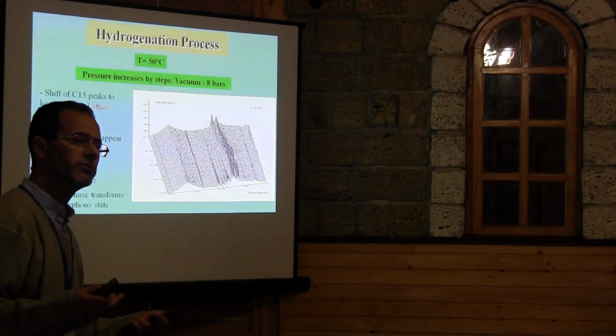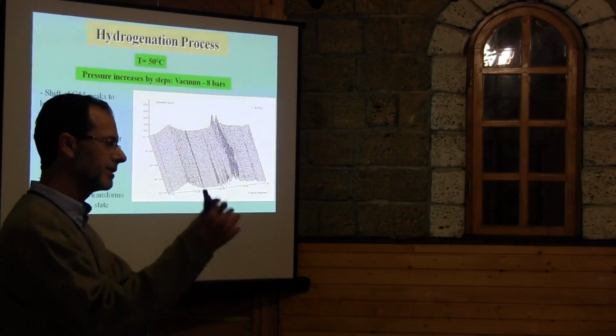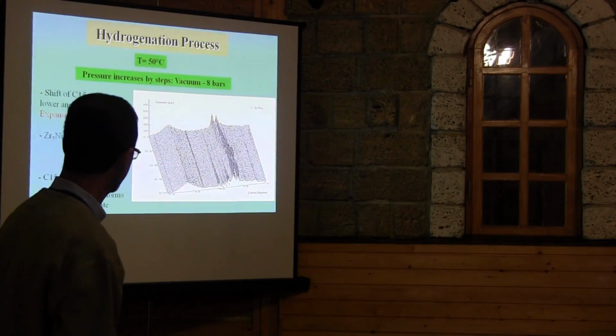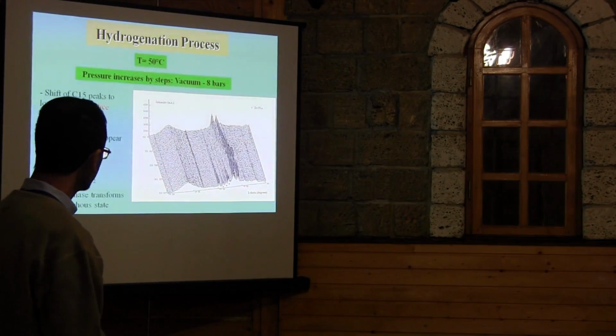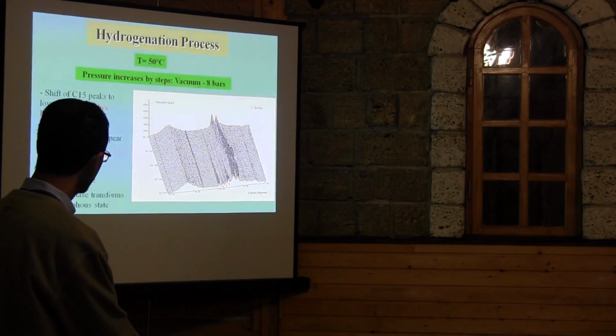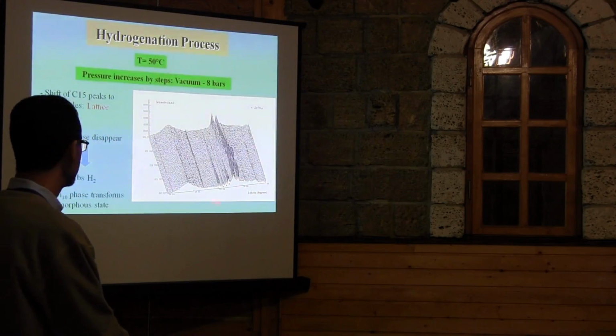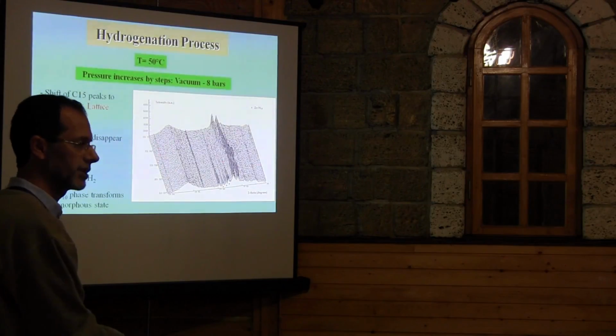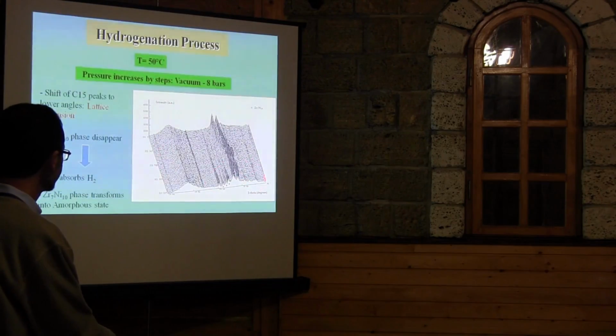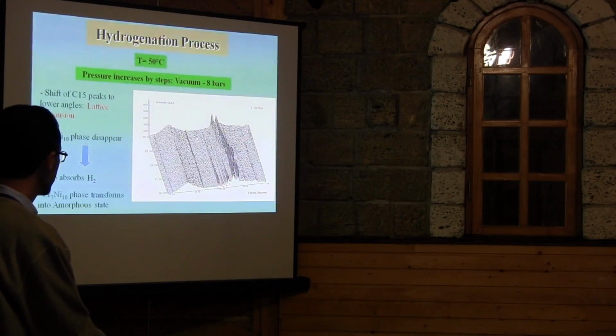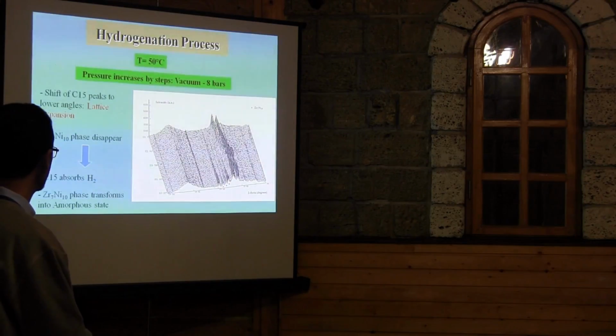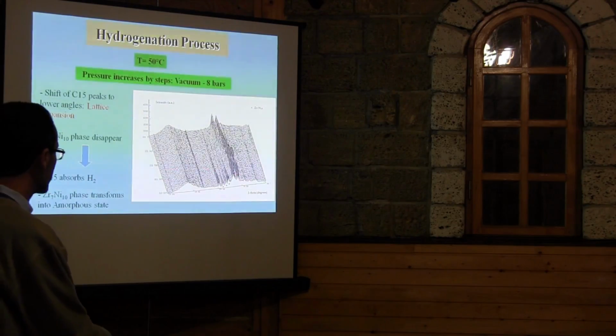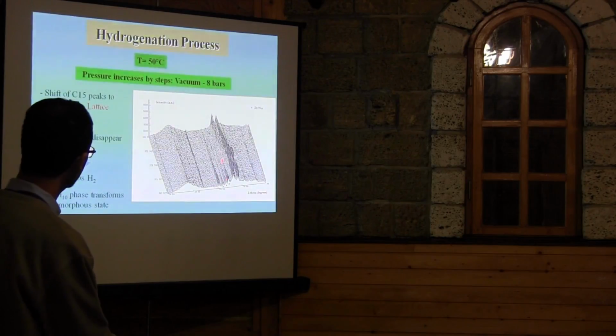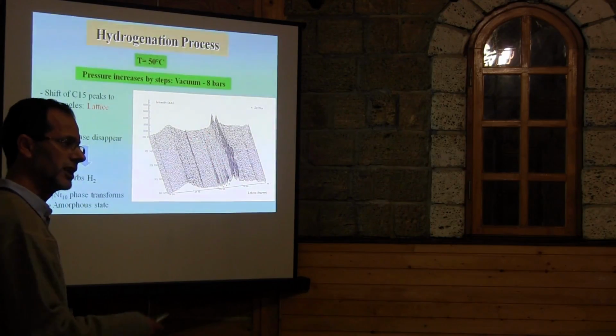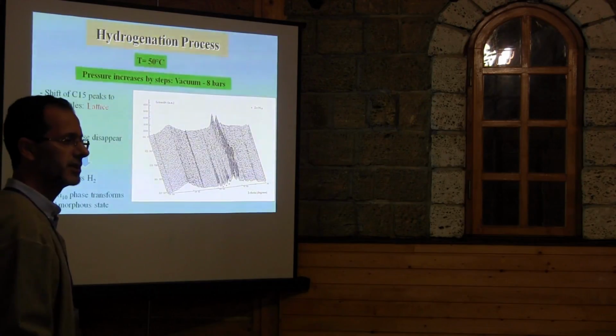Now I want to do in situ reaction. That means I put my sample under hydrogen atmosphere and I use neutron diffraction. We can see that with increasing hydrogen pressure, sorry, here, this is a recorded diagram. When I go from here to here, I increase the hydrogen pressure. You can see at the beginning, these two peaks belong to the cubic. These three star peaks belong to the secondary phase, which is zirconium 7 nickel 10. During the hydrogen interaction, you can see that these peaks disappear. Why? They are crystalline, and when they disappear, they become amorphous.